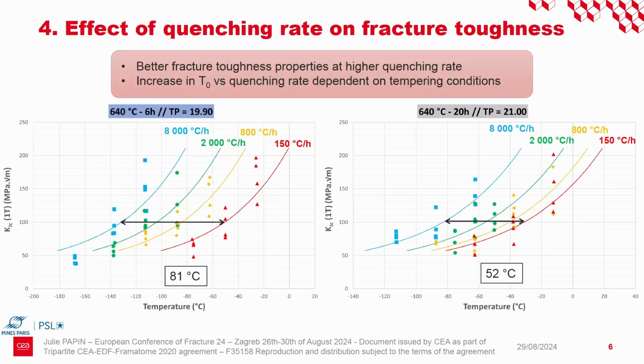Now, we will have a lot of master curves to compare. If we look at the effect of the quenching rate for the 2 tempering conditions, we can note that we have better fracture toughness properties at higher quenching rates. And also we can note that the increase in T0 versus the quenching rate depends on tempering condition.